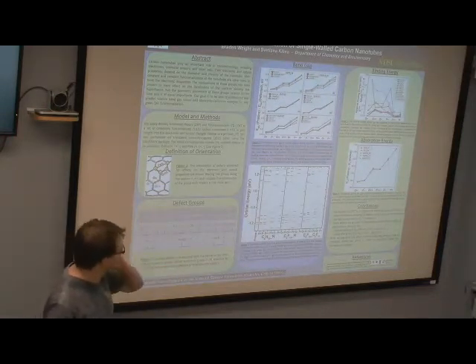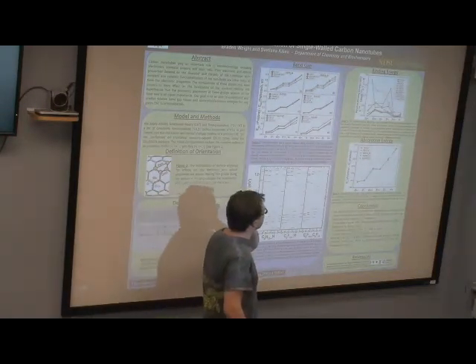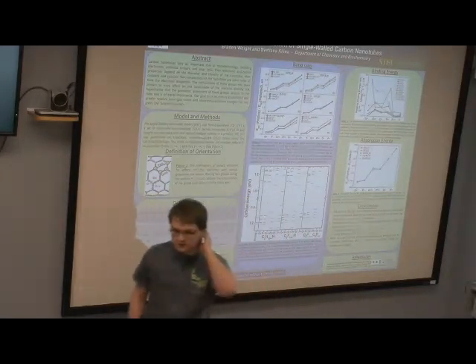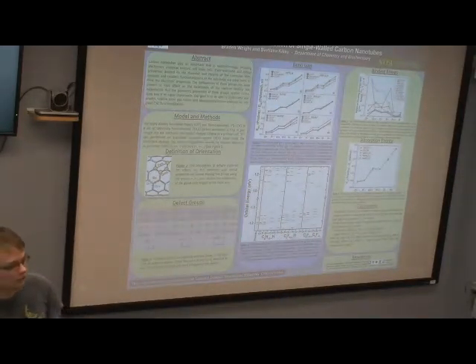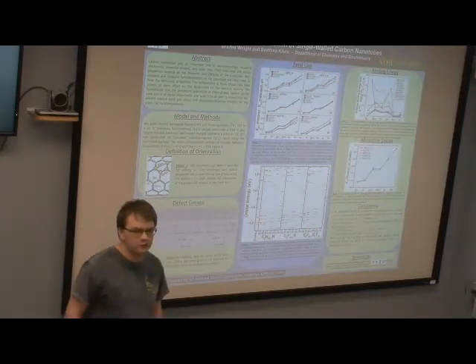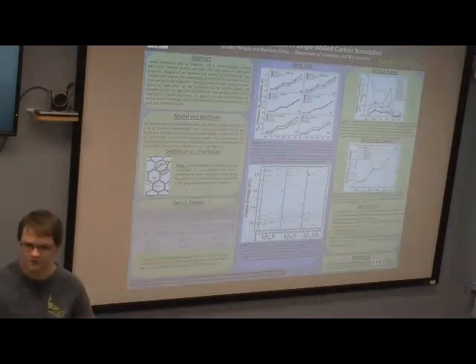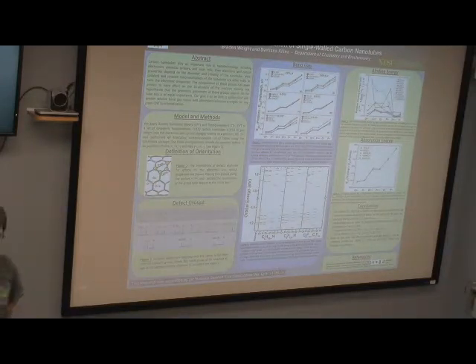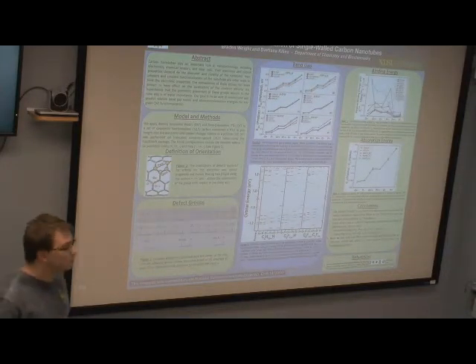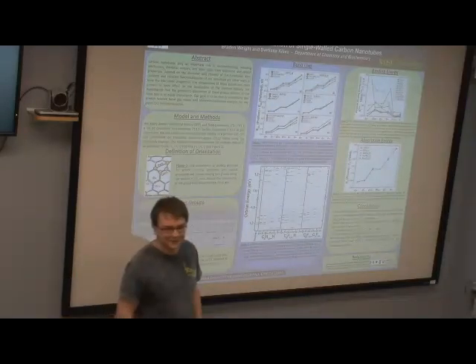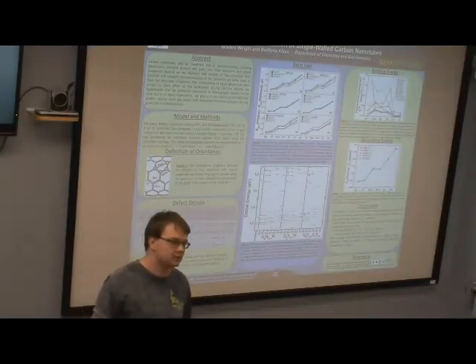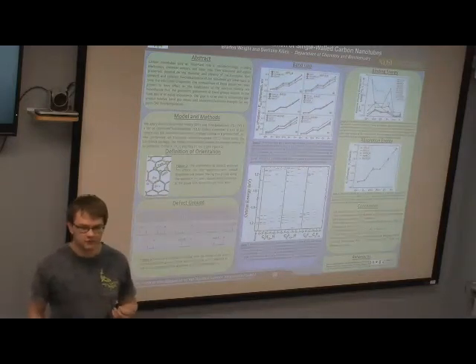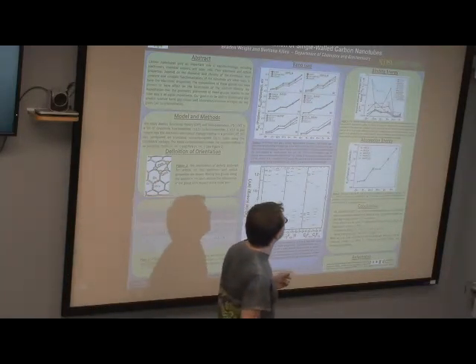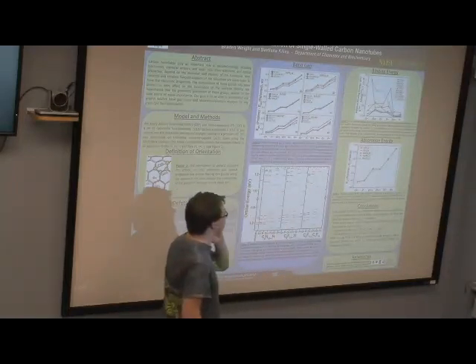So I think I was done explaining the molecular orbital chain. So then we can look at something else. We can look at the binding energy of these defects. Since we don't know the mechanism to create these defects, we would need to know the enthalpy of the reaction, the entropy, and whatnot. We can't compare across different defect groups, but we can compare across different defect orientations within the same group.